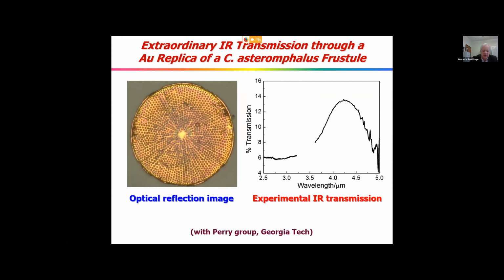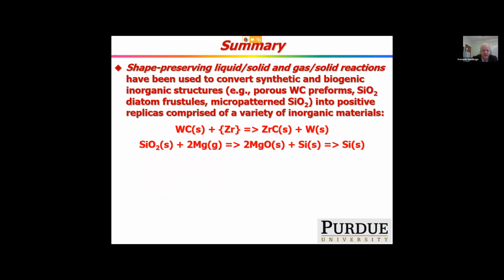This is with Joe Perry's group at Georgia Tech. You can see you get an enhancement in transmission, peaking at about 4.3 microns through this material. So this is a potential material that we could use by putting on detector molecules and detecting shifts in transmission for sensing applications.